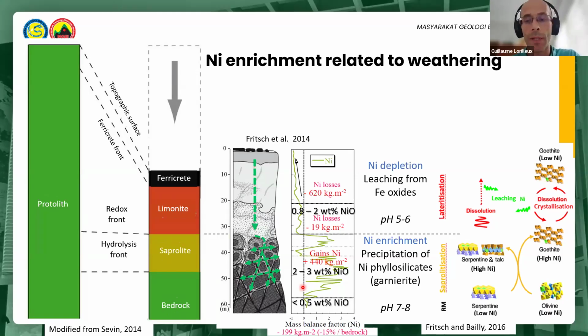Nickel in limonite is probably leached by downward circulation of acid meteoric waters, reducing the limonite grades to less than 2% nickel, and increasing the nickel grades in saprolite by precipitation of nickel-rich hydrous magnesium silicate, responsible for an absolute enrichment in saprolite. This is suggested and shown by mass balance calculations, as shown on this middle figure here, that show that nickel is lost in limonite and gains in saprolite. This leaching would be obviously favored by tectonic activity and structures controlling the underground fluid circulation.